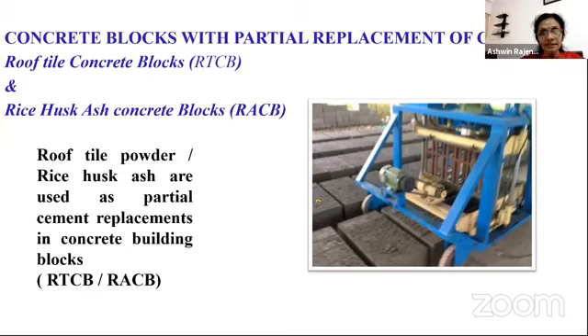Usually the rice husk is used in the rice mills as a fuel. It has fuel value. In earlier days also we were using rice husk for burning in the kitchen. We were using it as a fuel. So this rice husk ash, if it is burned under controlled conditions, will have amorphous silica, and that will have pozzolanic property, and it can also be used as a supplementary cementitious material. Definitely, if it is burned under controlled condition, it will have that property.